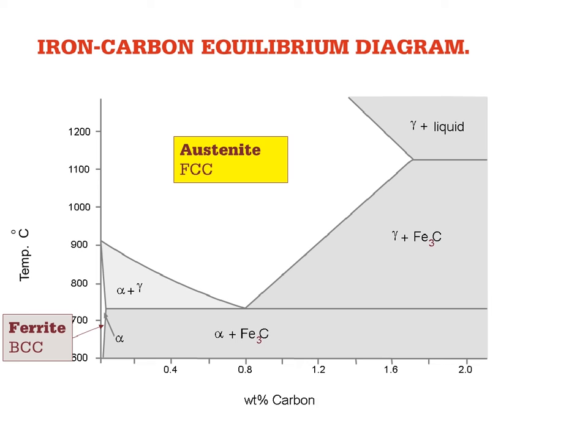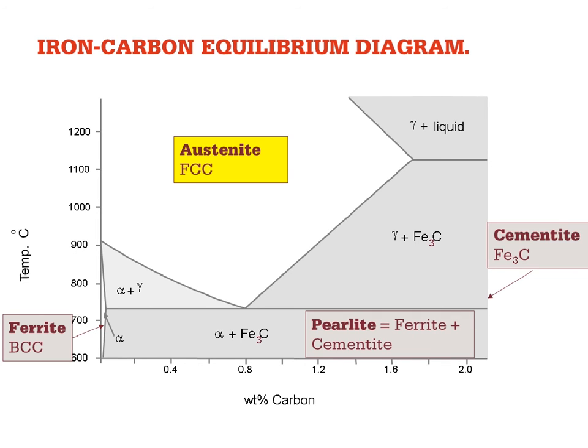When we come down to lower temperatures, that austenite becomes unstable and it will separate out into ferrite, which you can see marked there, has very, very low solubility of carbon, almost zero, and that exists below 900 degrees C. And then on the right-hand side of the diagram, you can see cementite, iron 3 carbide, which is rich in carbon. So the stripy pearlite structure that we were looking at just now is actually alternating layers of ferrite and cementite. And the morphology of that is critical in determining the strength and other properties of the steel.